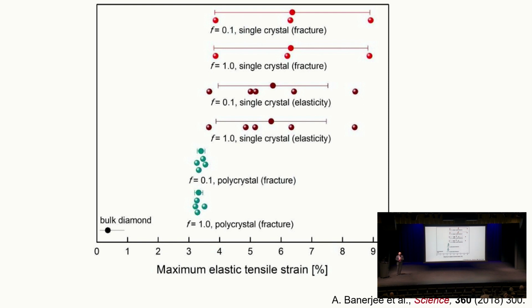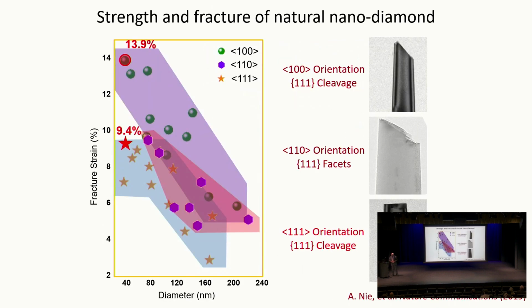Bulk diamond almost has no plasticity or inelasticity, which is known. So we published this in 2018. A group in China, at Zhejiang University, decided to test our results. Instead of synthetic diamond, they took natural diamond. They bought diamond, and they knew the crystallographic orientation.